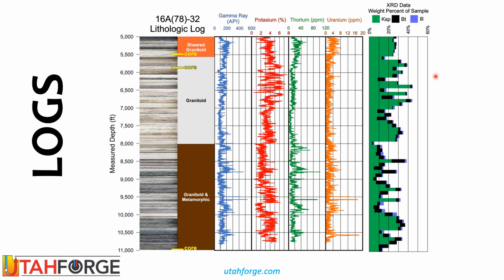And what I'd like to point out here is as you're coming down, the potassium is really variable, but high. And as we get down to 8,000 feet, which is where the granitoid and metamorphic rocks meet each other, it's also where there's a pretty good fracture zone. You get a big drop in potassium across the contact. That also shows up in the XRD data. It's masked a little bit in the overall radiation or gamma log by increases in thorium and uranium.